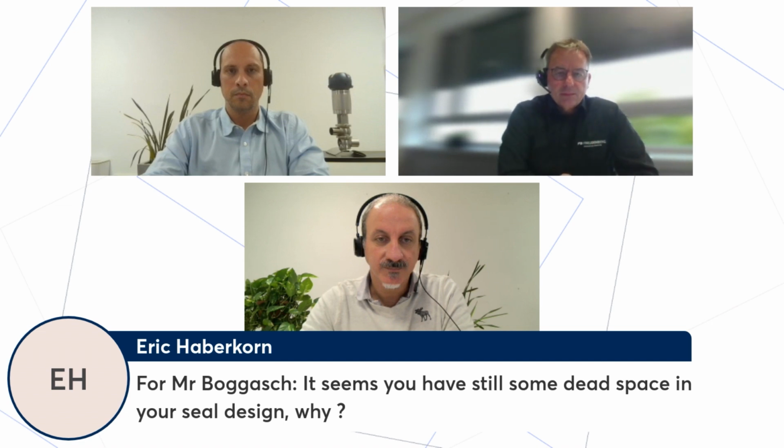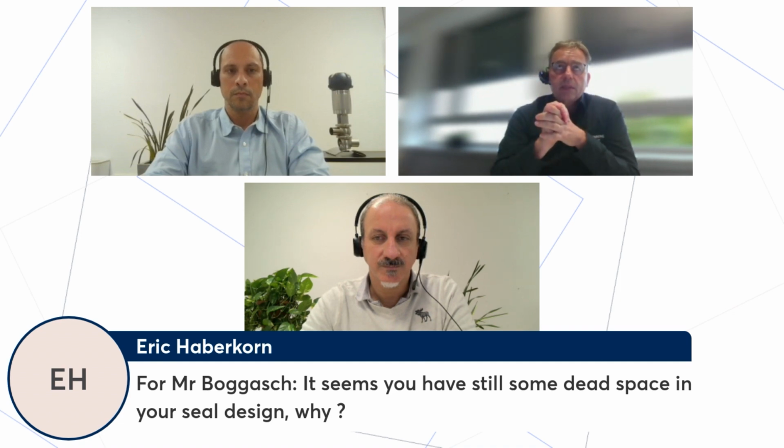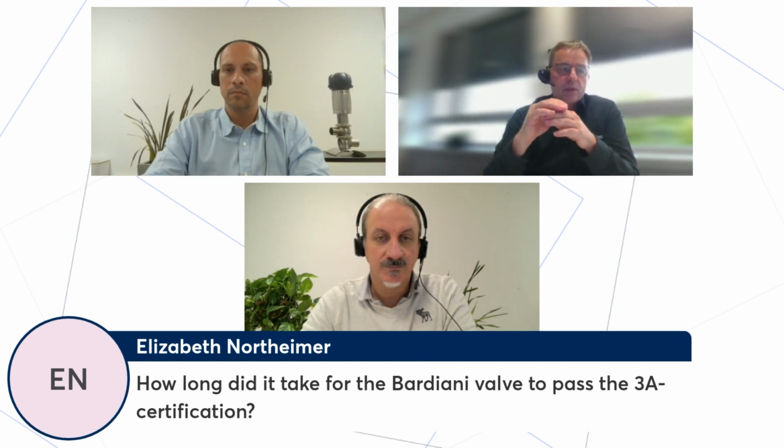Yes, it's a good question. I think you see this rectangular free space at the back of the seal. So we have some free space or dead space. But at the end, for elastomer seals, you need some room for expansion because you have a higher thermal expansion coefficient and you have some tolerances to handle. So you need some space. And important is that this area is really far away from the media, so it can't be filled by media from the media side. Sometimes it's possible to have the expansion area in the direction of the media, but in general, that's not so. So you have to design somewhere a space for the expansion of the elastomer.